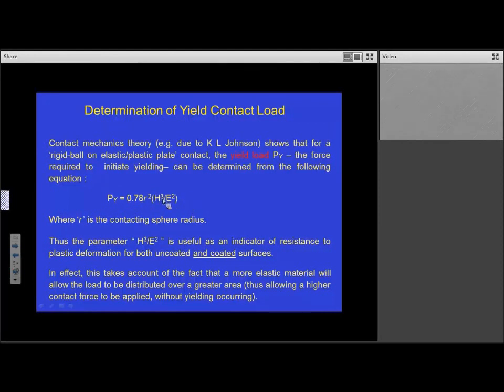Again, you see here there's H cubed over E squared, so it tells us again that H over E is important. This is basically related to the fact that an elastic surface can spread the load more, and therefore you have to apply a greater load in order to make it yield if the surface is more elastic, has a lower elastic modulus. So that's where that particular formula comes from. Some people think this is a purer form of H over E. In fact, it's not. It's specific to a hemispherical indenter against a surface.